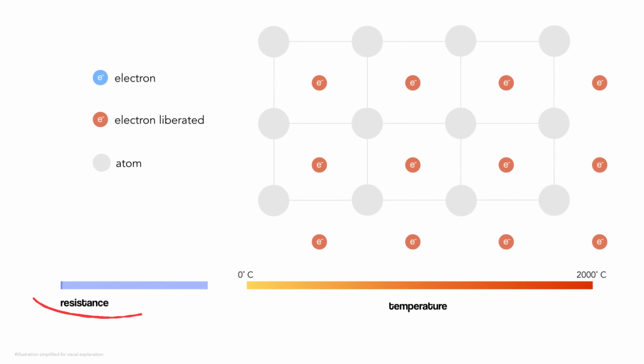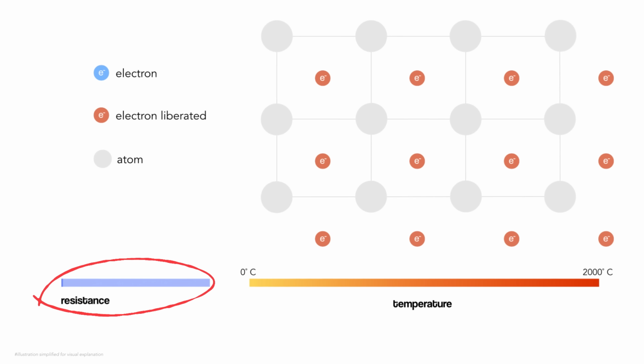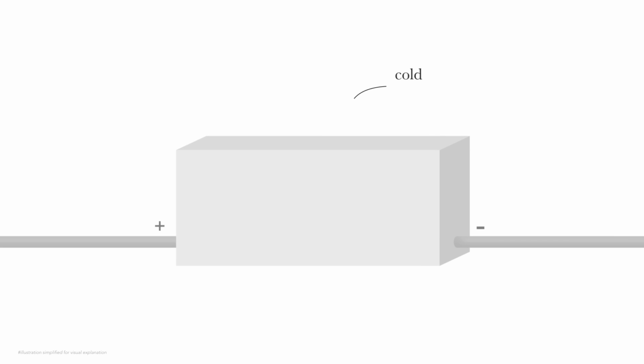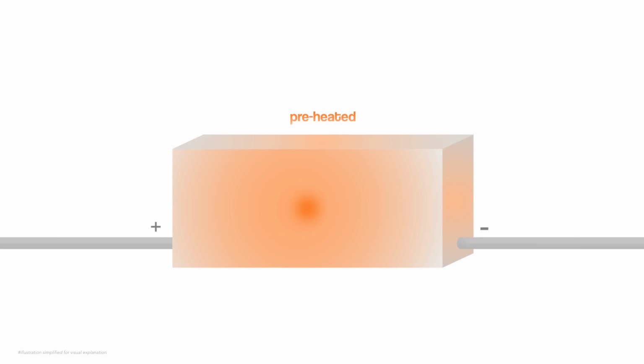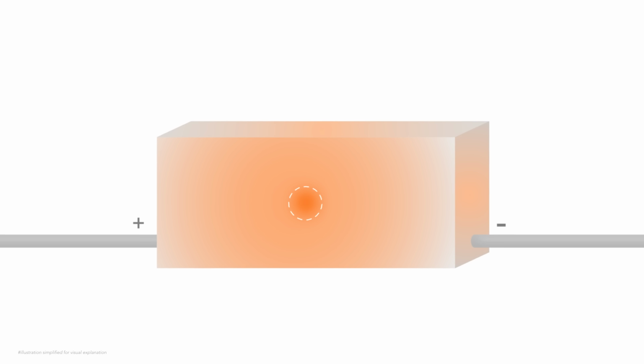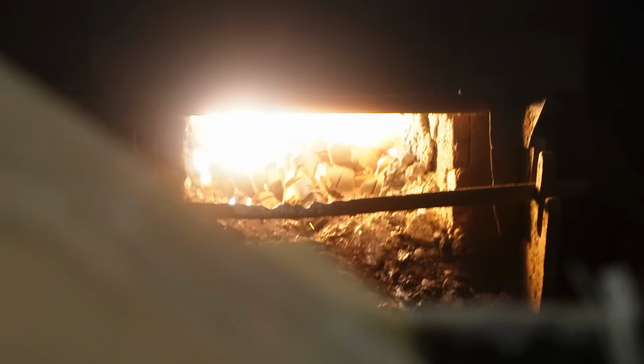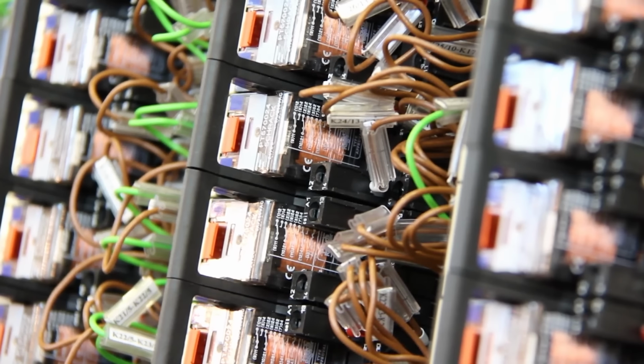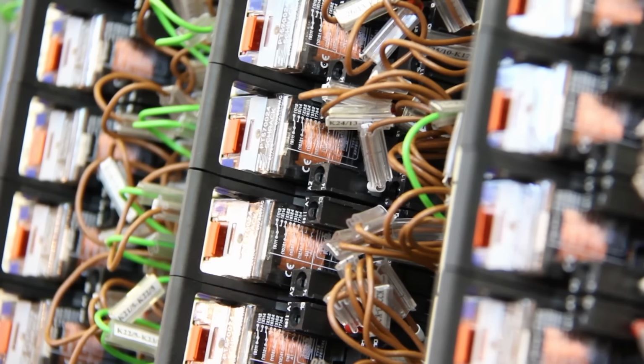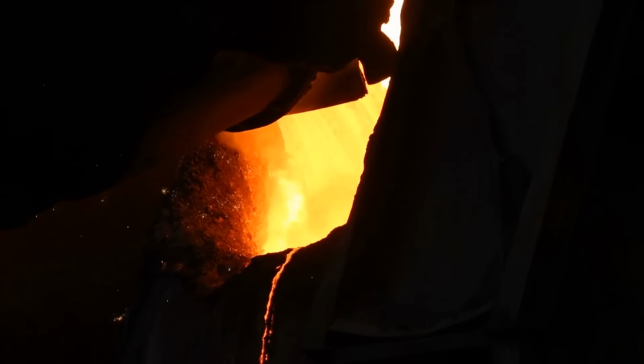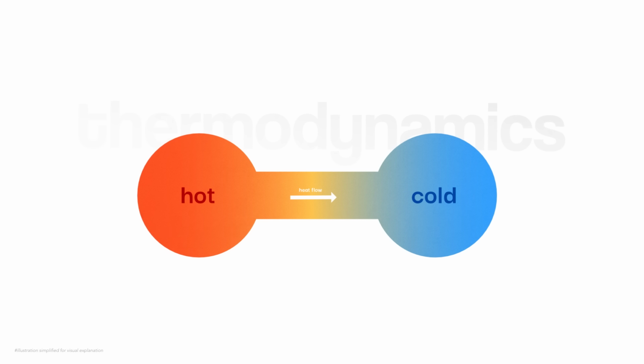An interesting catch is that this falling resistance opens up a different engineering challenge. Firstly, a cold solid oxide barely conducts, so it often has to be preheated before it's switched on. Then, once hot, any spot that runs slightly hotter than its neighbour pulls in more current, because it has less resistance and therefore heats up further, which can cause it to run away with itself in heating. This normally means that oxide ceramic heaters need to account for this in the power delivery and control, though I don't know how this works at such high temperatures, as the thermodynamics can get a little bit strange.